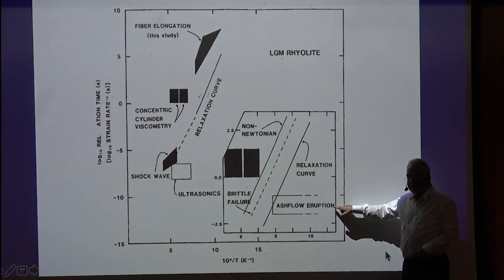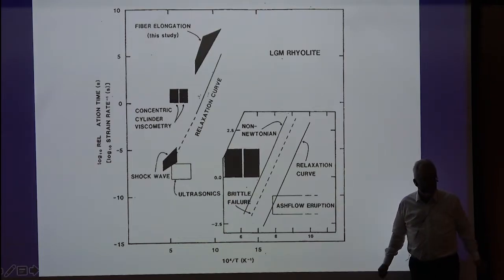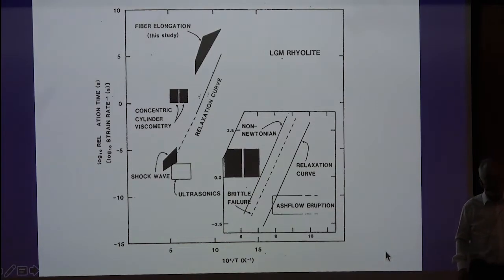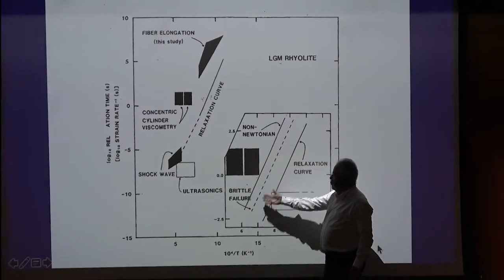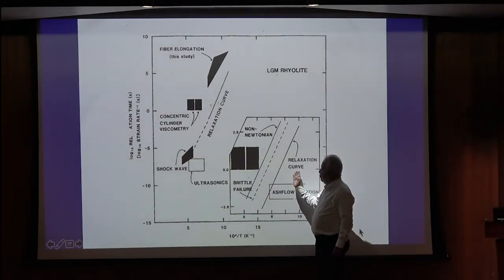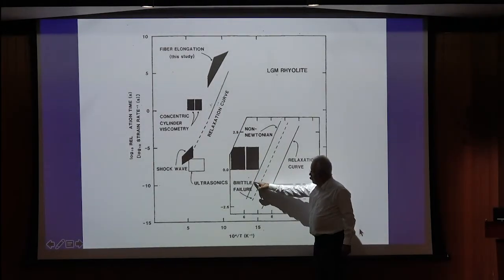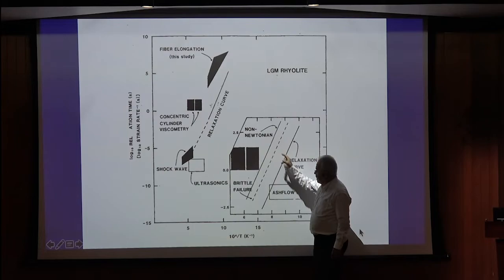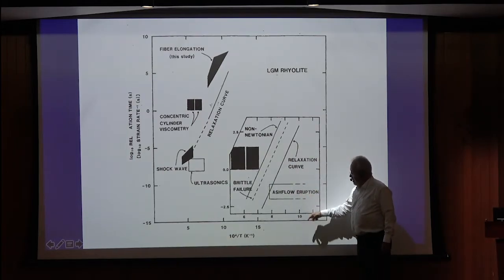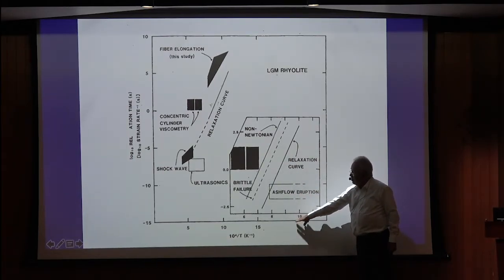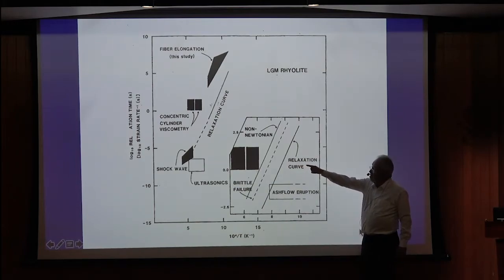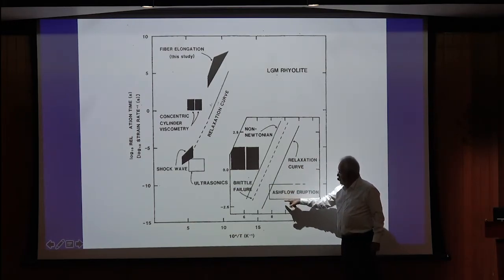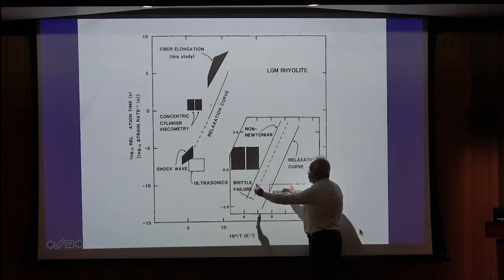And I knew that if I went into a paper and wrote "eruption," I was opening myself up because I had no expertise beyond what I read in textbooks. The basic idea was this is the material boundary between flow and failure, the brittle fracture criteria here, and the calculation of the temperature in reciprocal temperature here and relaxation rate or strain rate estimated from the literature was very close to the estimation of the material failure.